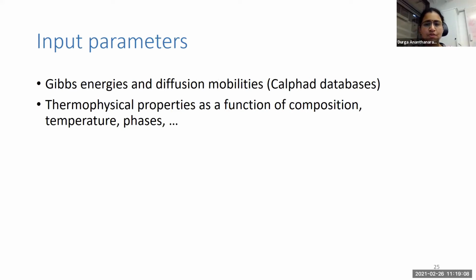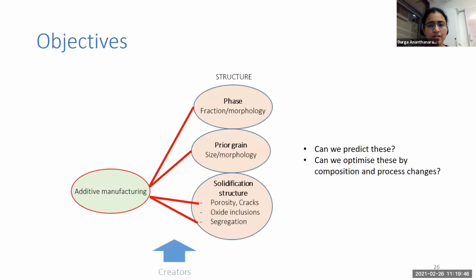So as we saw in all of these, there are several key input parameters that are required. And one of them is, of course, the Gibbs energies and the diffusion mobilities that we have to take from CALPHAD databases. So even though we are not calculating bulk equilibrium, we saw that we still need these as input for our models. So the reliability of these input parameters is of paramount importance. Then we also have thermophysical properties that we would ideally need as a function of composition, temperature, and for different phases. So that's also another challenge that we face in terms of input parameters. Okay, so that was a bit of background on how to approach all these different phenomena.